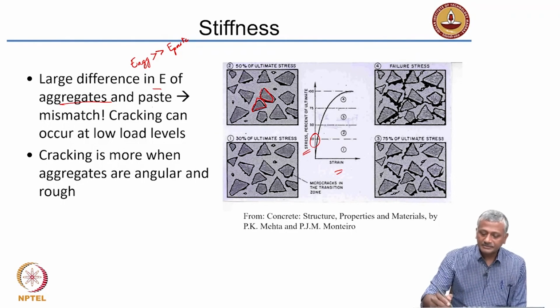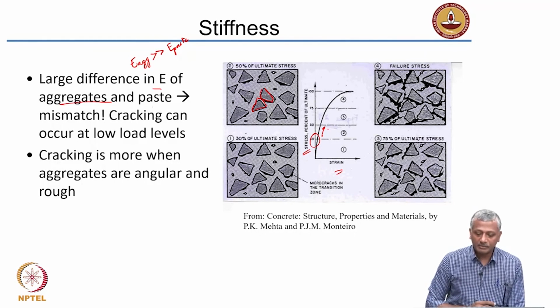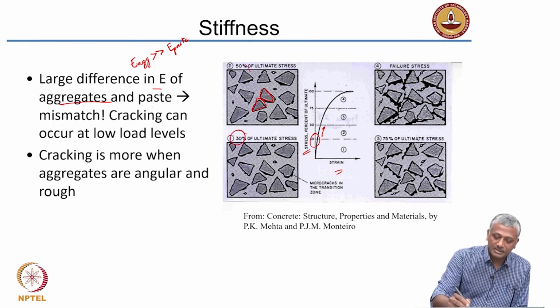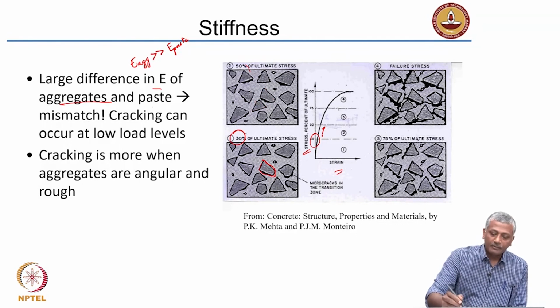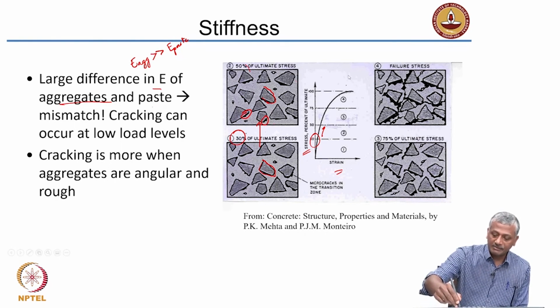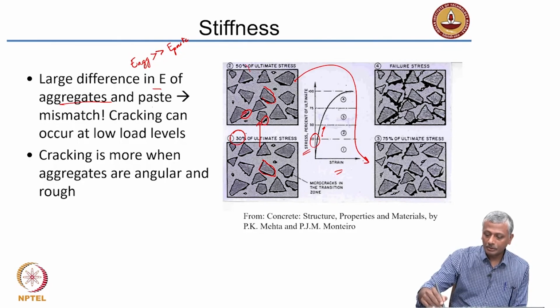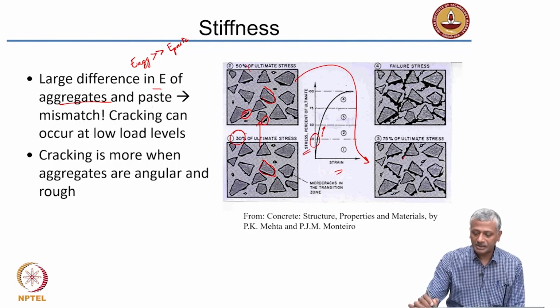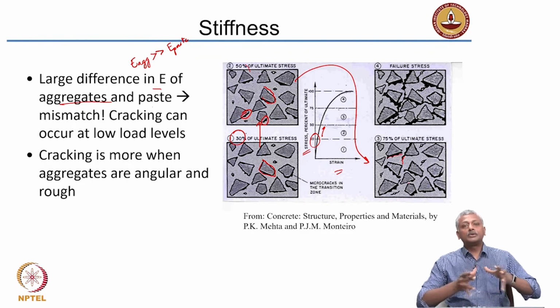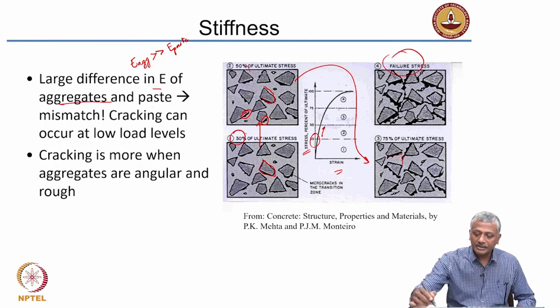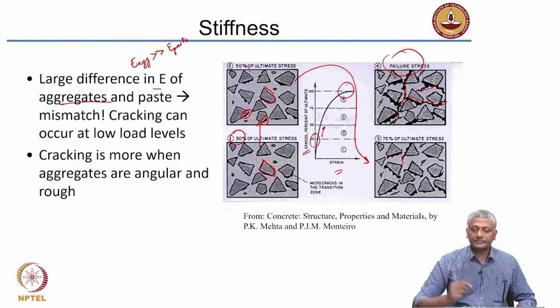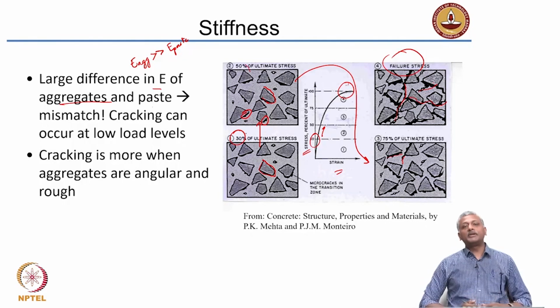As the load level becomes higher, I am sorry, this was 50%. So, this is 30%. The zone around the aggregate has cracking already. When you increase the load, the cracks around the aggregate become larger. When you further increase the load to 75%, the cracks that were around the aggregate have started going out into the paste. And then close to failure at the top point here, these cracks have started forming networks. So, you start forming a crack network which basically leads to a complete collapse of the concrete.